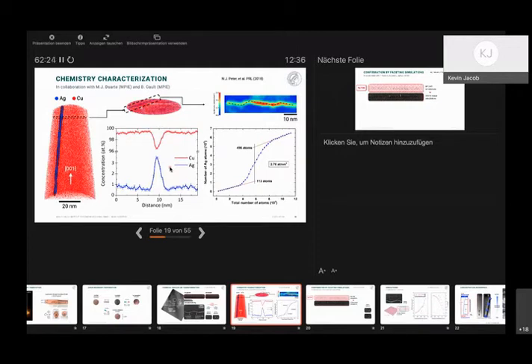Yes, so the good thing is in atom probe you detect individual atoms, right? So there's a certain loss, but in principle the 3D gives you all the atoms that have been detected. So this 1D profile is taken from a cylinder. You always choose a cylinder which contains a certain amount of atoms, and from this cylinder you then calculate how many atoms are silver, how many atoms are copper, and from this you calculate your 1D profile, if that answers your question. Yeah, so you're telling basically to go for a cylindrical region of interest and convert that.